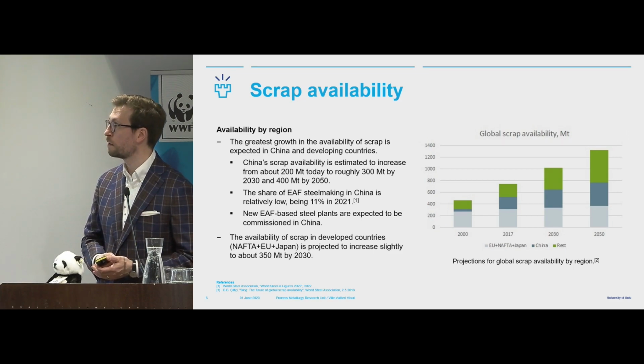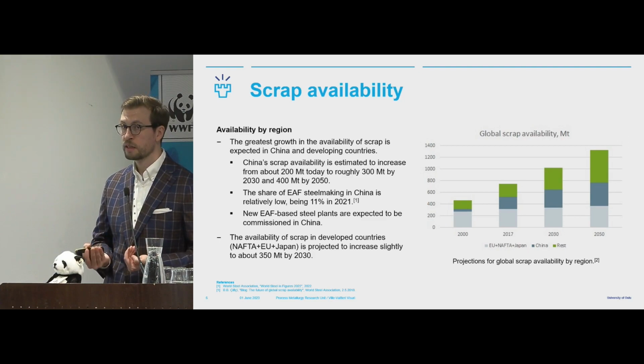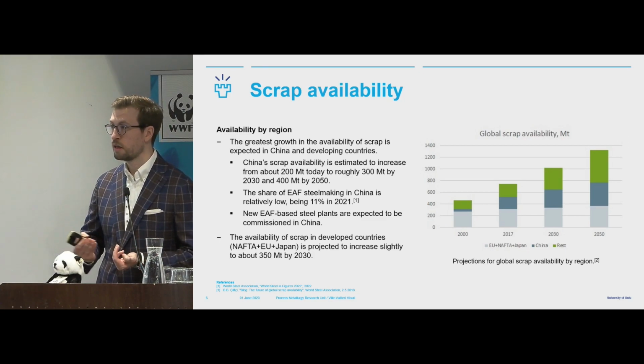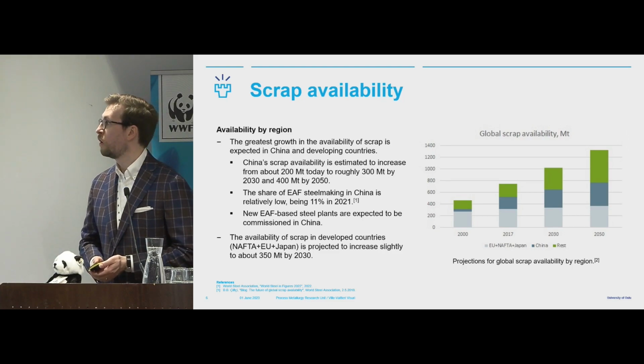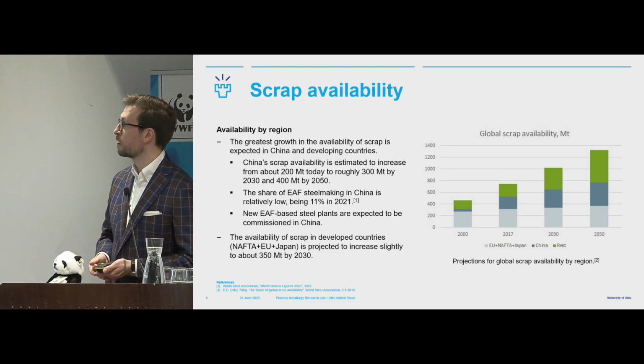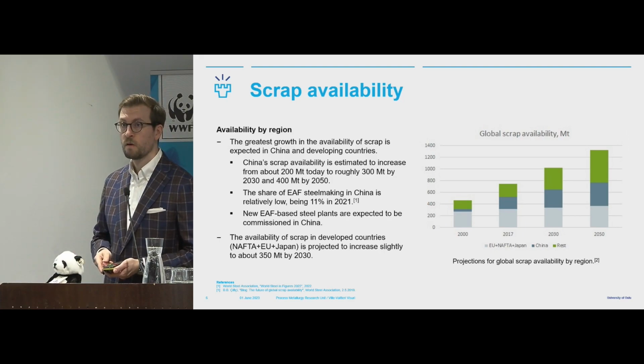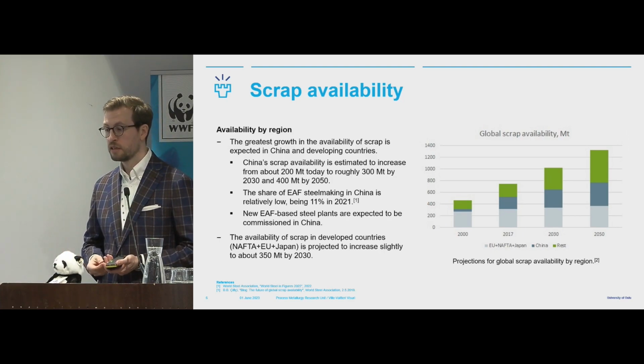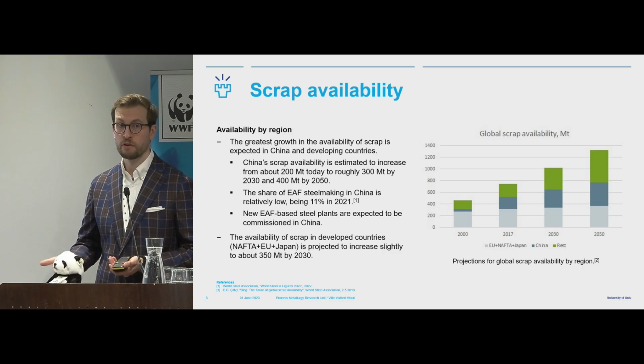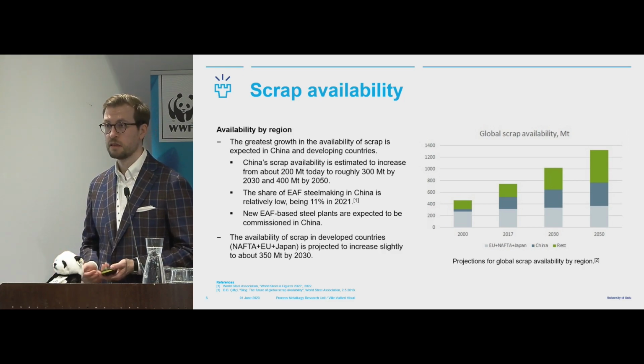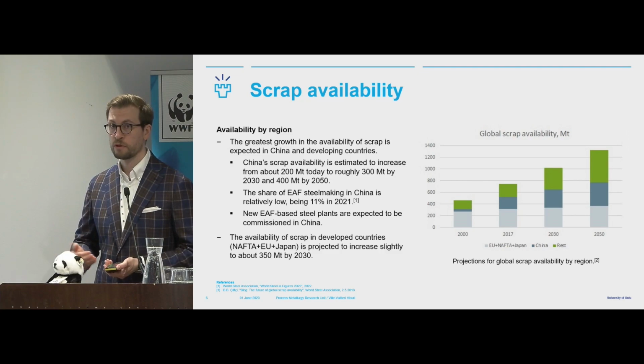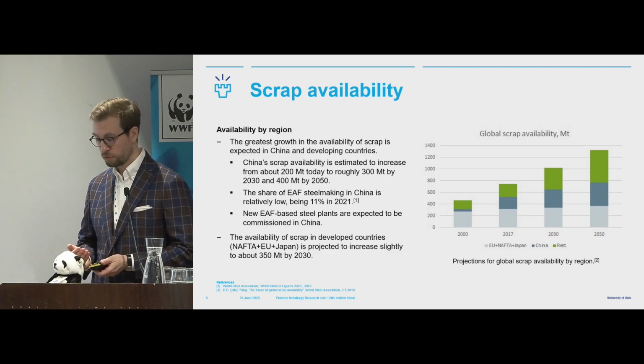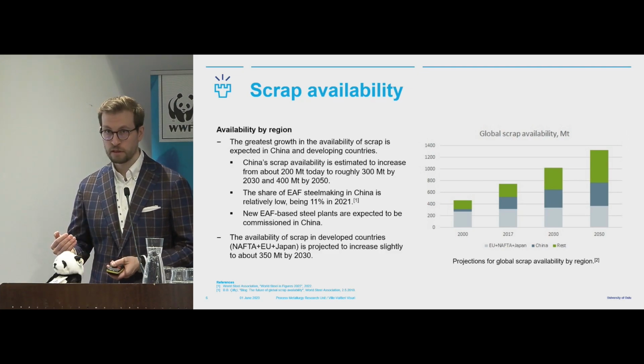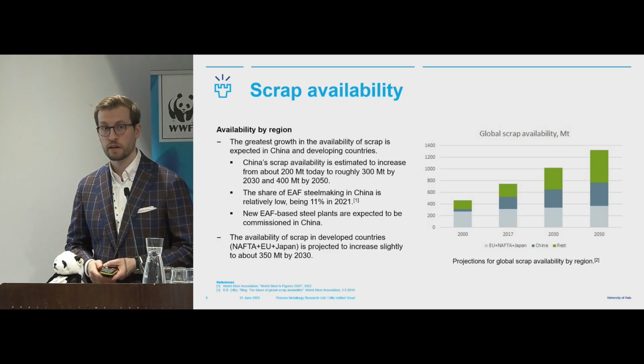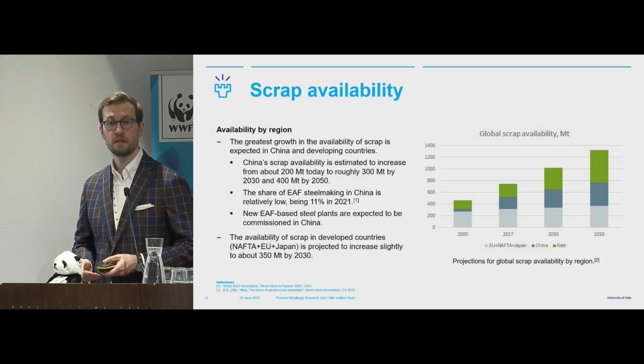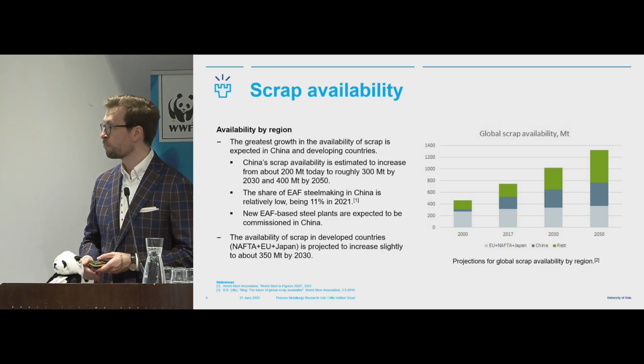Then looking at the availability by region, the availability of scrap is not increasing everywhere at the same pace. We have much more scrap becoming available in the developing countries, and especially in China. And at the same time, the Chinese steel industry is using much less electric arc furnaces than the Western counterparts. So this means that there's a huge potential to increase the scrap use in China. And probably this could mean that investments take place in China to increase the production capacity using electric arc furnaces.